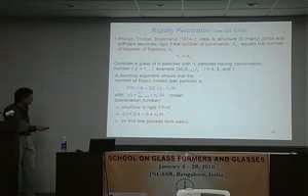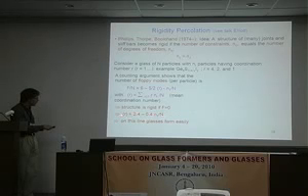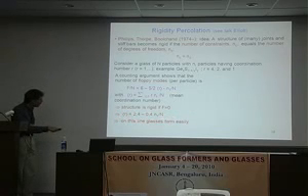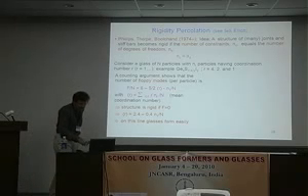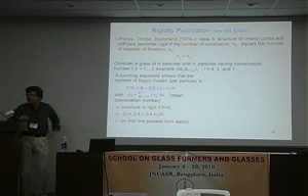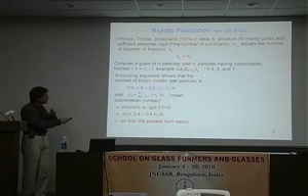And so if you set this equal to 0, you see you have a correlation between the mean coordination number and, in this case, the number of atoms that have only 1 bond, which is given by this here. And so if you have this relation, that the mean coordination number is given by this expression, you should easily form a glass. This here is in 3 dimensions. And indeed, this is really for this case here.